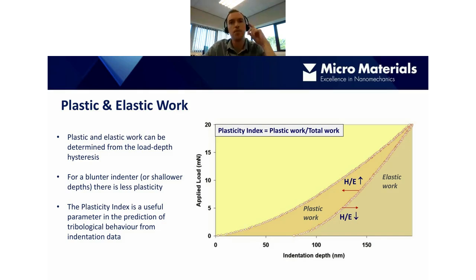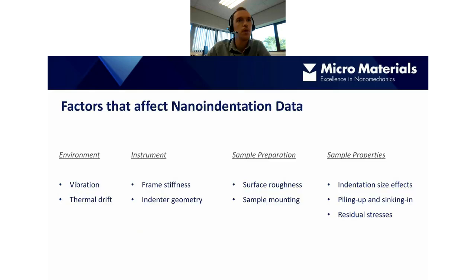So there are a few indexes, such as the plasticity index, which is the plastic work divided by the total work, and also the hardness to modulus ratio, so simply the hardness divided by the modulus. We can use these indexes or parameters as a useful prediction in terms of tribological behavior from indentation data. So my colleague Adrian might talk more about that later on.